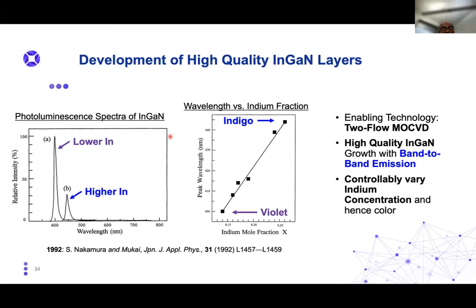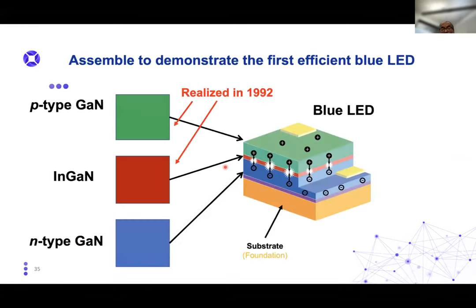Because at that time, several groups tried indium gallium nitride growth, but there was no emission at all at room temperature. But using two-flow MOCVD, we could observe the first blue and violet emission using PL. So that's another big breakthrough. We could solve the two problems, the indium gallium nitride emitting layer and P-type gallium nitride, in 1992 using two-flow MOCVD. And we stacked these three layers on a sapphire substrate.